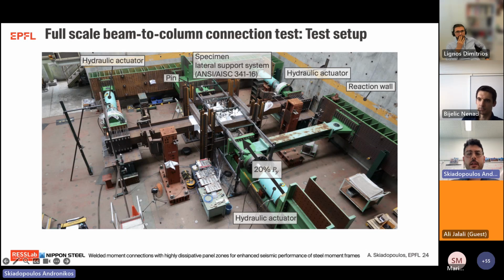The interior beam loaded beam to column connection was tested horizontally as shown here in this figure. 2 displacement control actuators imposed the lateral loading in the steel beam ends, and these were attached to the beam ends through the aid of adapter plates. And the pin connection was realized in the column north location as you see it in this figure. And with regards to the column south location, a hydraulic actuator was imposing a constant compressive axial load that equals 20% of the axial load capacity constantly throughout loading. Also, the beam to column connection was supported laterally by a system that was designed according to the American code.